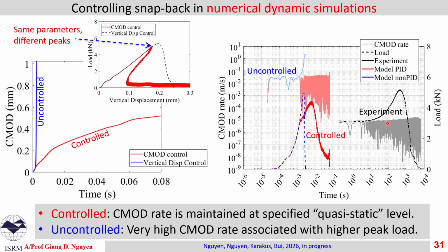As you can see here, the crack opening displacement follows what we expect. When we compare with the test data, of course, we are not yet able to match the test data in terms of the rate, because the rate used in experiments is very low, 10 to the power minus 5 meters per second. In the simulation, the red well-controlled one is about 10 to the power minus 2 meters per second. At the moment of crack initiation, you can see the jump in the load in the uncontrollable test is associated with the jump in the opening, while in the controllable one, using crack mouth opening displacement control, the very stable opening rate leads to a lower peak load.